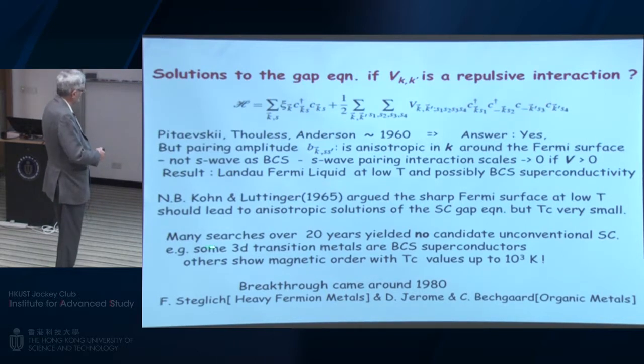Some transition metals were actually BCS-like superconductors. Others show magnetic order, and magnetic order can have Tcs like iron up to 1,000 Kelvin, which was very high. But there was no sign of unconventional superconductors, that's to say non-S-wave superconductors. But a breakthrough came around 1980 in two directions. Frank Steglich in Germany discovered heavy fermion metals, which were low-temperature superconductors.